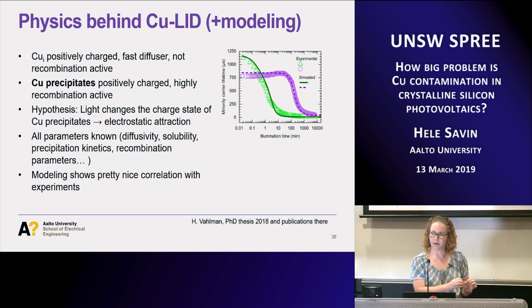Then we know that there are these very dangerous copper precipitates, which, on the other hand, are highly recombination active. But they are also positively charged. So in normal conditions, at room temperature, copper won't precipitate easily, because there is a repulsion between positive and positive charge. But if we shine light on our samples, we increase our Fermi level so that we actually change the charge state of our copper precipitates, so they become negative or neutral. So under illumination, we have negatively charged copper precipitates, and then we have lots of these positively charged interstitial coppers, which will start to precipitate. So this is our hypothesis of what will happen.